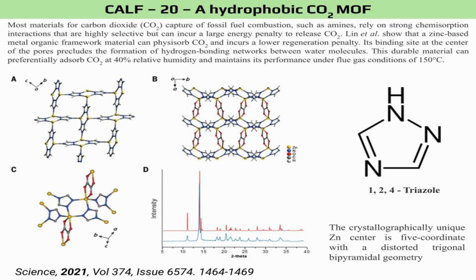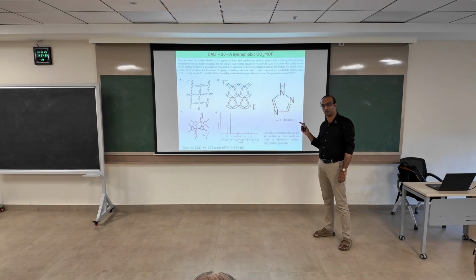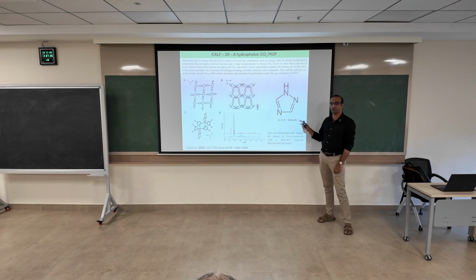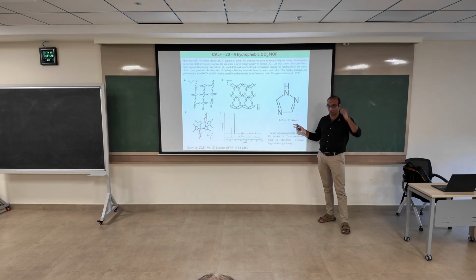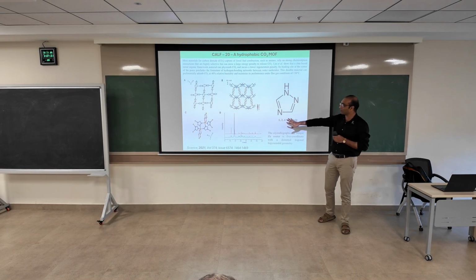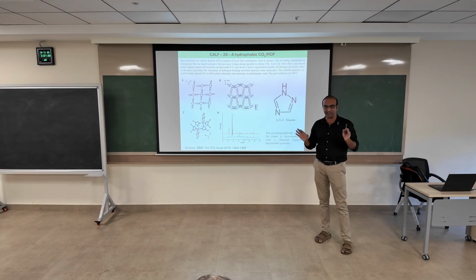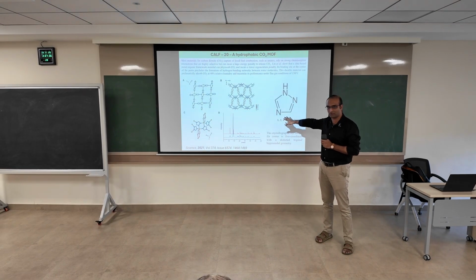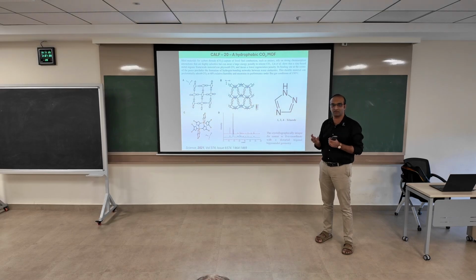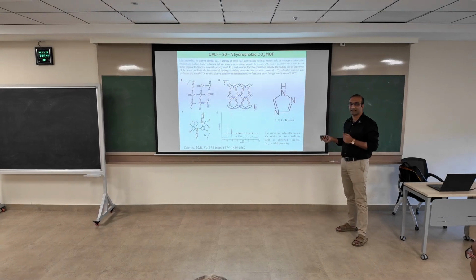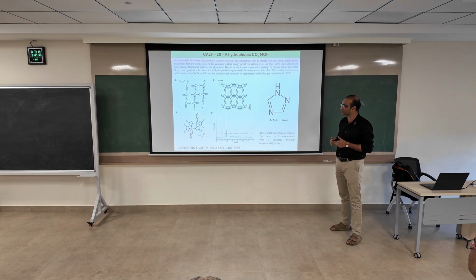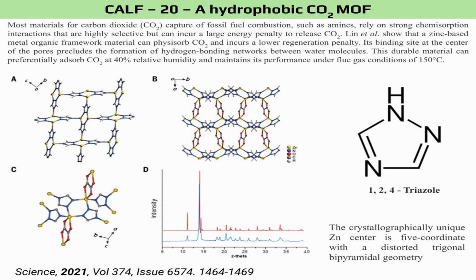So as an alternative, you have this MOF. The reason I'm showing this particular MOF is that it has arrived at commercialization and is being made in large scale quantities. BASF and a company called Svante in Europe have commercialized this, and they're selling it for people who want to use it in their facilities. Okay. So this particular MOF can be made very quickly, in kg scale quantity without any problem, and it requires a very simple ligand, and then some zinc salt, and you can make this linkage, and they have this interpenetrated structure where you have a zinc triazolate linkage in the middle.